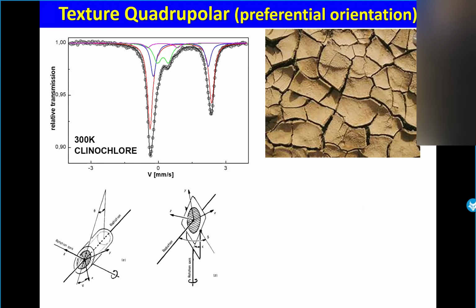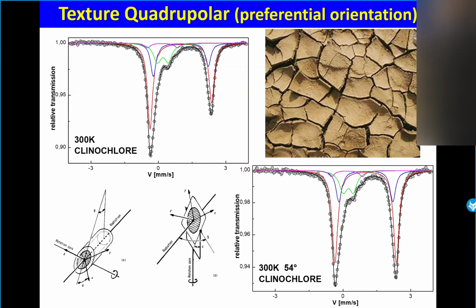And there is a solution: to rotate the sample at the magic angle. By rotating the sample, we have the same sample but a different spectrum, except that the angle of the gamma beam differs from that of the classical one. And you can see that now it's possible to describe the spectrum with doublets, with Lorentzian lines, with same intensities. So that means that it's very important in some cases to check the origin of the intensity difference between the two lines. Okay?